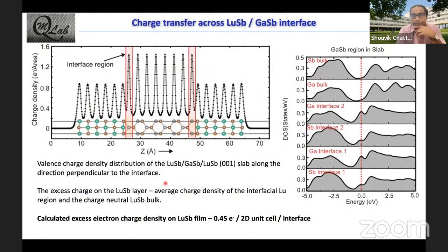So now, we also see there's another thing that is happening at the interface. That is, there is also a charge transfer across the interface, which we can calculate to be about 0.45 electrons per 2D unit cell per interface going to the lutetium antimony side, and also to the gallium antimonide side, though it's very small, which is about 0.05 electrons. And this you can see when we plot this layer resolved density of states.